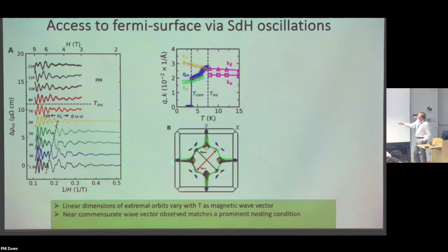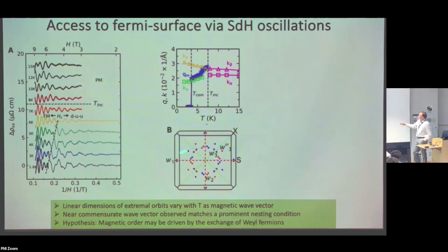Now, underneath these Fermi surfaces lie all the Weyl points. So the Weyl points are actually quite close to the chemical potential. So these are quite small pockets. The electron density is quite low, but very strongly impacted by the presence of these Weyl points. And so therein lies the assertion that the RKKY interactions are actually mediated by, we could call Weyl fermions, because they are fermions that are very close in momentum space to a Weyl point.